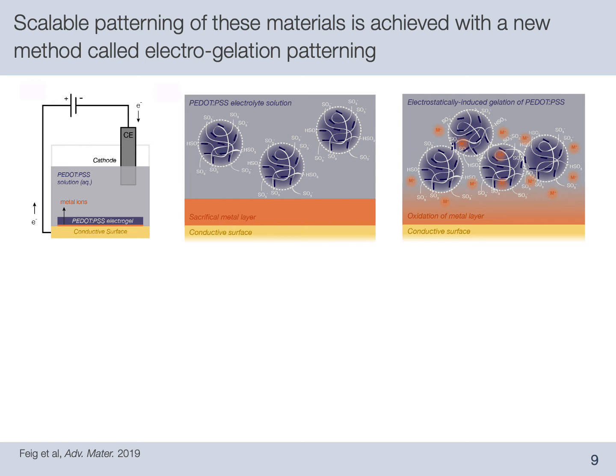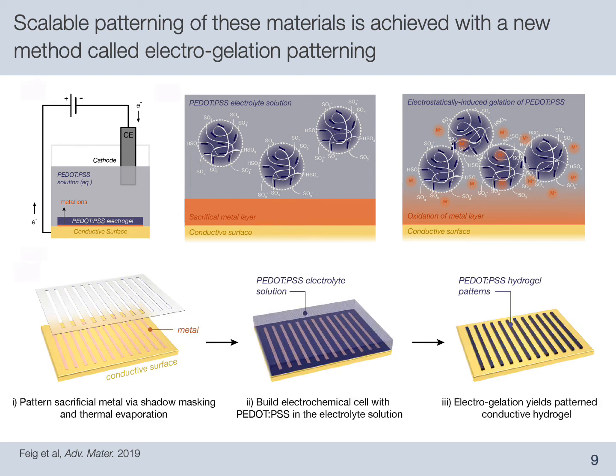PEDOT:PSS at the interface. This phenomenon enables us to take advantage of much more well-established techniques for patterning metal thin films, including evaporation through a shadow mask. Using that pattern as a working electrode in an electrochemical cell with PEDOT:PSS solution as the electrolyte, we can then use electrochemistry to transform the sacrificial pattern into a patterned conductive hydrogel.